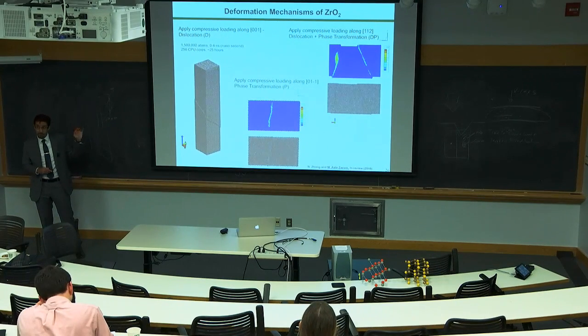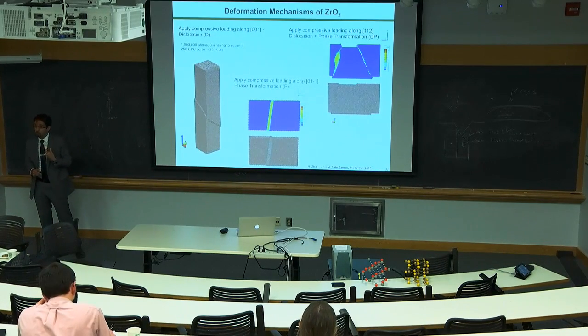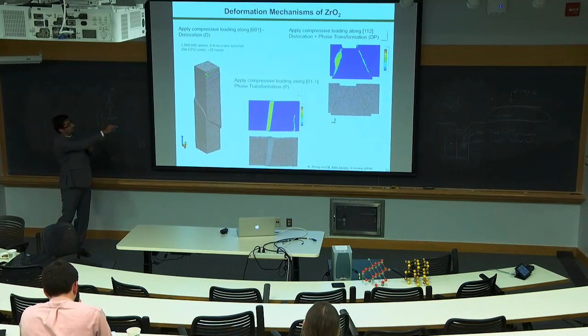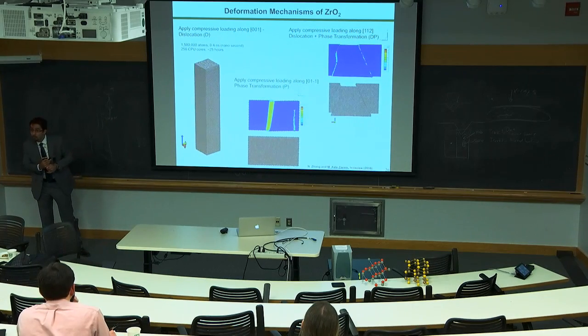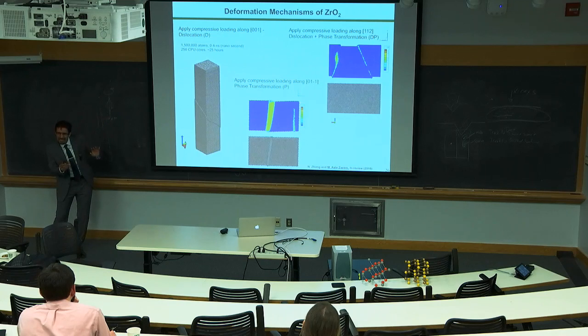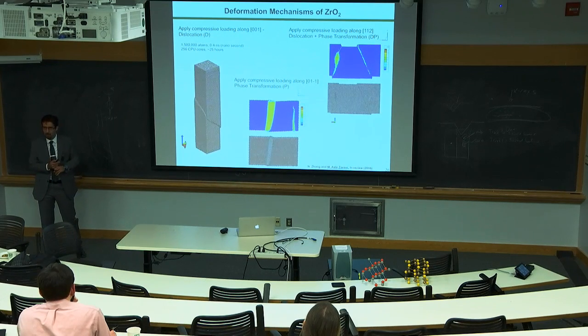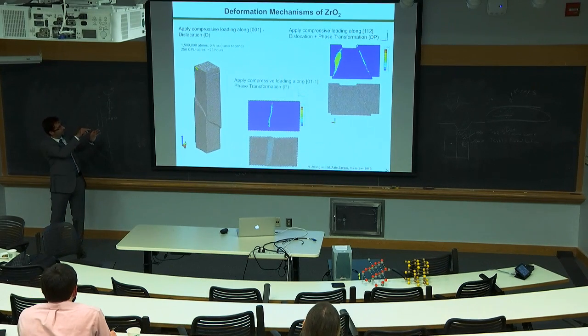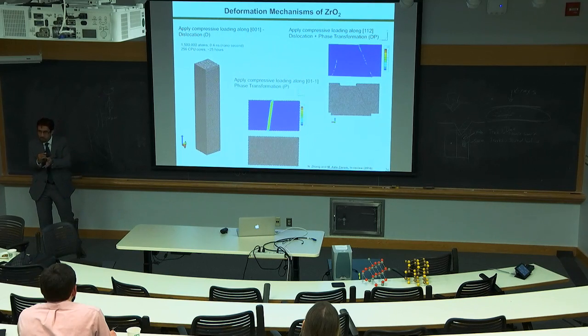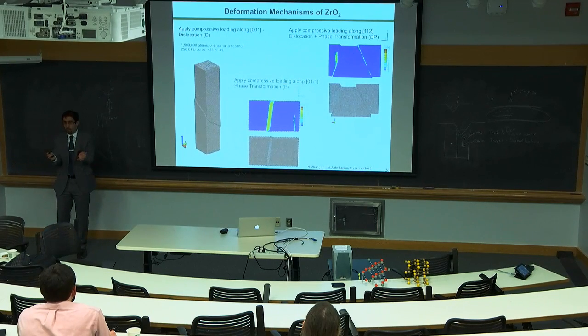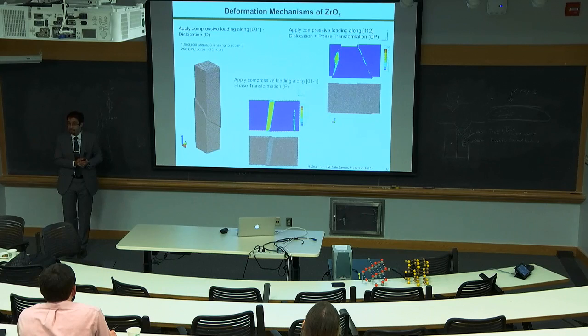If you remember, the experimental filament size was 1 micron. This is about 25 nanometers. So if we make it less than 10 nanometers, less than 5 nanometers, at these scales it is going to behave completely differently. So yes, we need to do size scale effect studies as well.